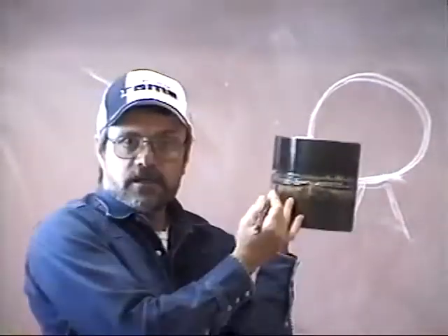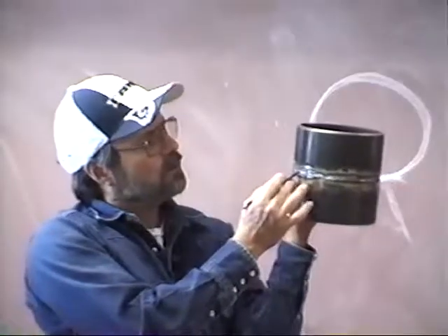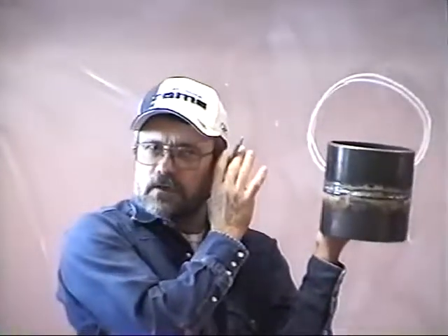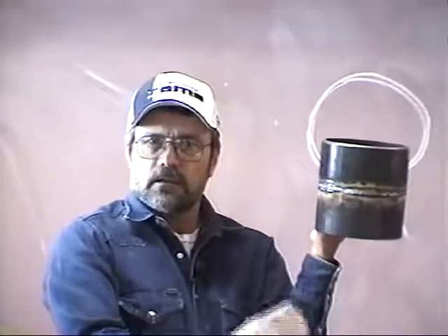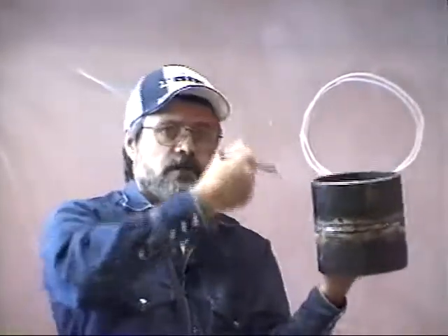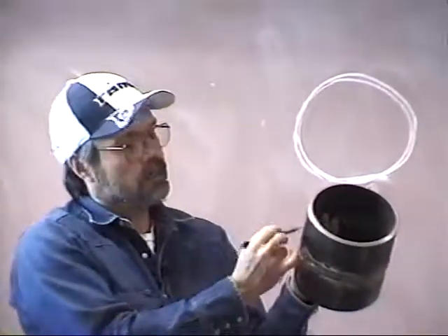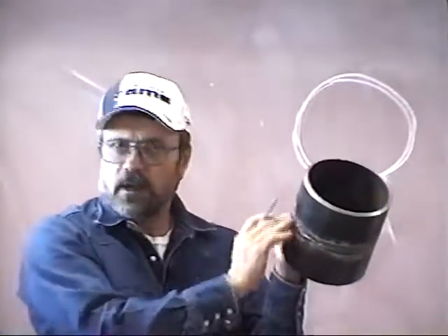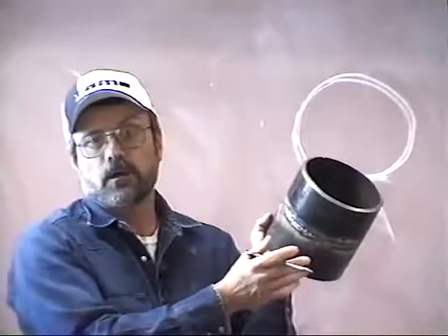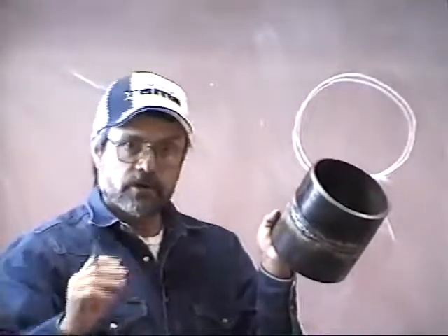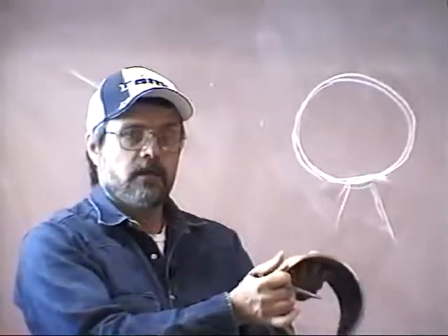Now, if you're welding across here and it's getting too small, you're not sure you're hearing that sound, stop immediately. Stop immediately, clean off the inside, check, look, see if you're getting any penetration. If you're not, then you've got to go back and you're going to have to clean that up, grind it up. You may even have to remove some of the weld that you've already deposited and then increase your amperage and go back in again.